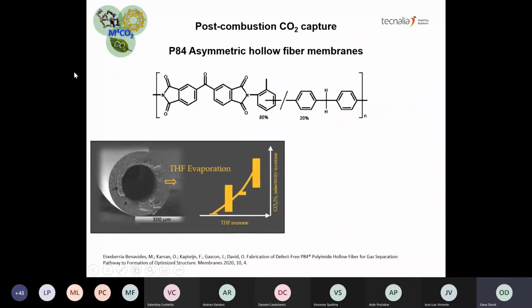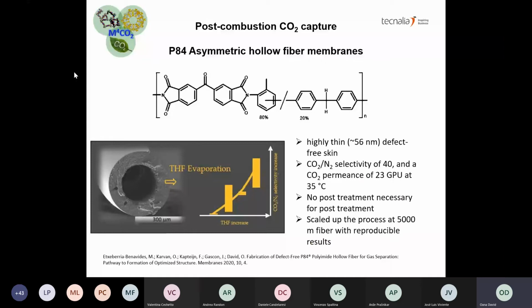So with P84, we managed to make a hollow fiber membrane with a very thin skin without any defects, about 56 nanometers. And we didn't need to do any post-treatment in order to seal any defect because there were none. We managed to scale up the process, but the permeance was 23 GPU, so it's much lower than the objective for post-combustion carbon dioxide capture.